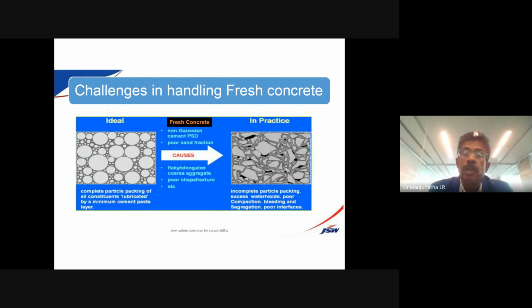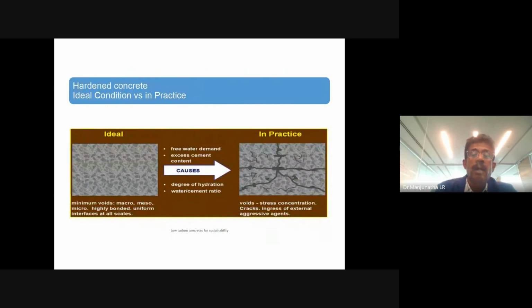It will be affected a little bit. So we need to really work the fresh state of concrete. When the concrete is hardened, when it is set, we are looking for a reduction in shrinkage cracks, ingress of external aggressive agents, and voids. It is very important to work closely with making concrete: free water demand, excess cement content. When designing mixes, how to regulate the water content, the degree of hydration, and the water cement ratio all play a very important role.